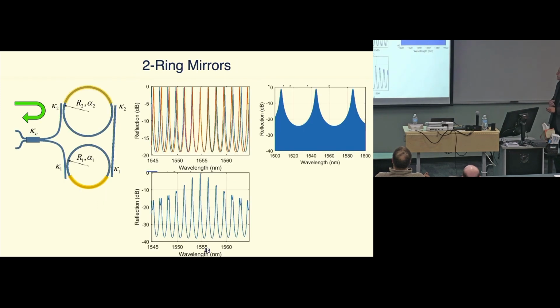So what we're doing is just this. We have 2 rings, different diameters, so they line up at 1 wavelength. They get successively offset, and then eventually it comes back in phase again. Depending upon how different you are, that changes the spacing and how close this one is versus where this is. We want this other line to be outside the gain width of the material, so we push that out where the laser, we don't want it to lase at this and this wavelength. It needs to be single wavelength.